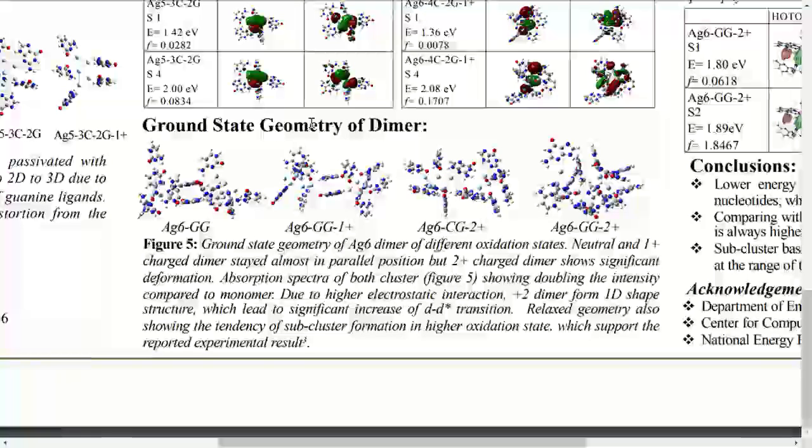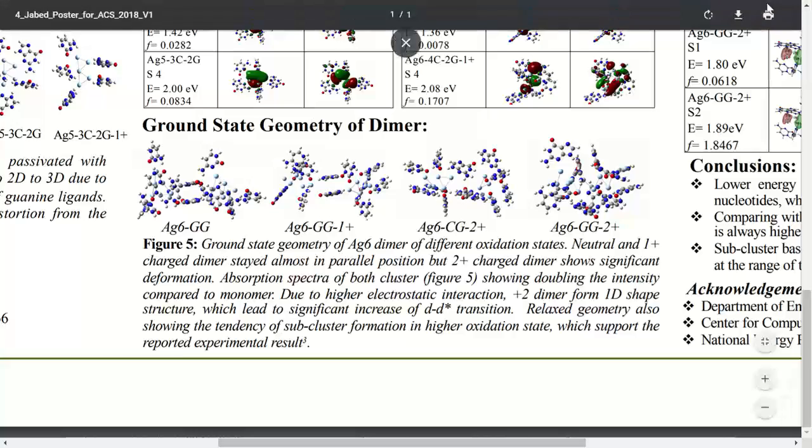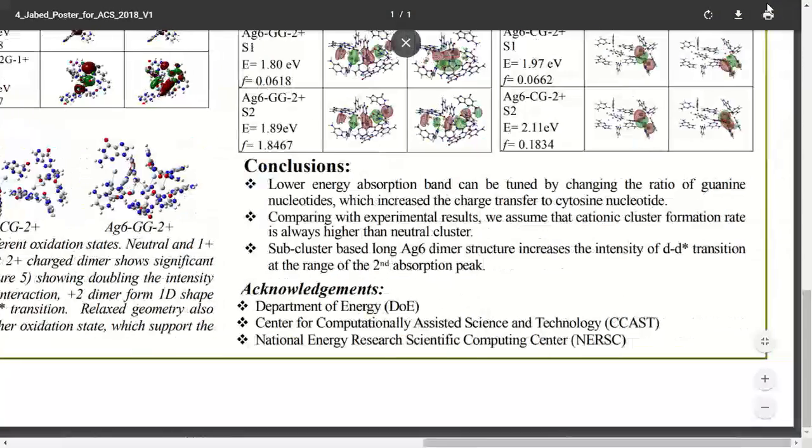So in the next studies, I just form a dimer. In the dimer formations, as I said, they have no confirmed conformation mechanism of formation. So we thought that maybe it's not a direct dimer formation. They are separate, and form a dimer through the pi stacking of the different ligands. So I consider the different ligands, indicating the ligand pi stacking. I formed the different dimer, and then optimized that dimer to look at the final structure.